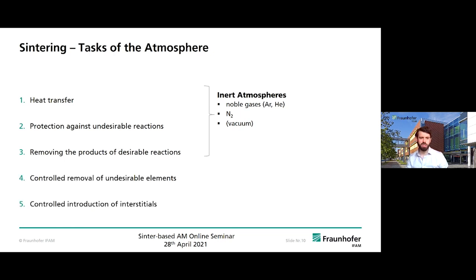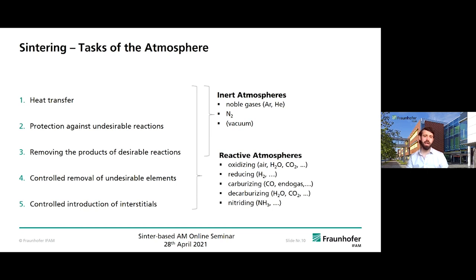And there are two more tasks of the atmosphere. It's a controlled removal of undesirable elements like oxides on the surface of the materials, and a controlled introduction of interstitials like nitrogen or carbon, which you may know from case hardening. This, additionally to the first three tasks, can be done with reactive atmospheres. To mention there are mostly hydrogen or endo exogases.